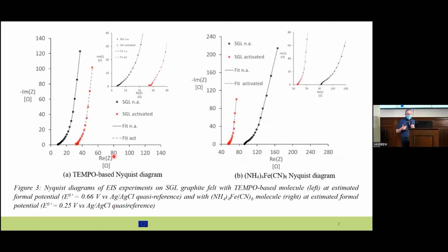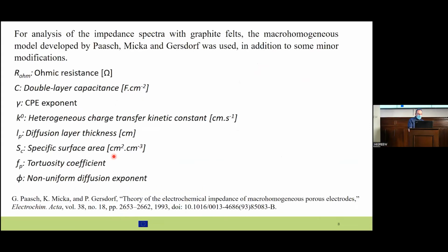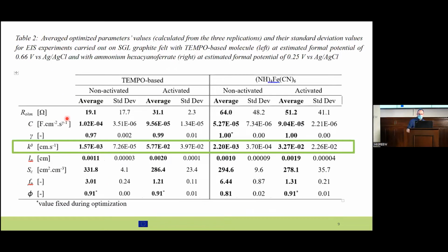We went further. We implemented electrochemical impedance spectroscopy, in similar conditions. I do not go into the detail of the experiment because I'm not the expert, I confess. We analyzed this electrochemical impedance spectroscopy with a macro-homogeneous model that allows us to extract different parameters. The parameter we are especially interested in is this heterogeneous charge transfer kinetic constant. There are a lot of parameters, so for sure we will have a good agreement between the experimental data and one version of the optimal parameters. It's not so easy to fit, but at the end, we can get this kind of value.